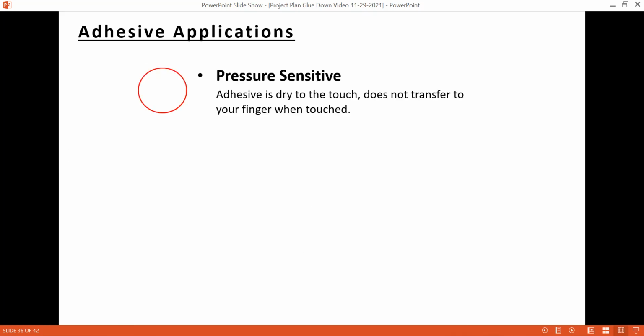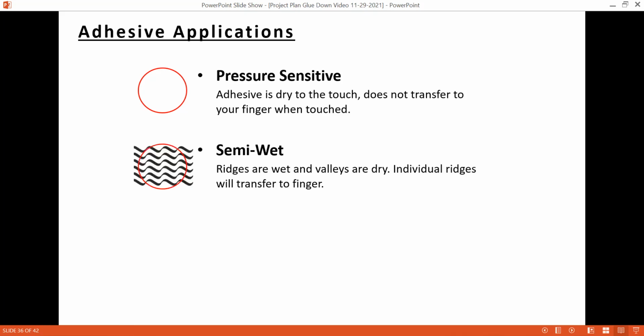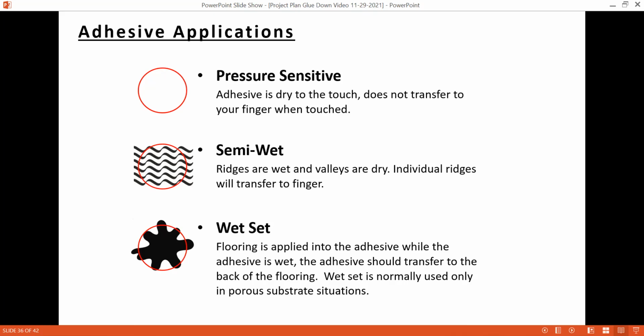Adhesive applications are often referred to as pressure sensitive. This is where the adhesive is dry to the touch. It does not transfer to the finger when touched. Semi-wet refers to the adhesive when the ridges are still somewhat wet and the valleys are dry. Adhesive will transfer individual ridges to the finger when touched and will transfer some of the adhesive to the back of the flooring. Wet set refers to installing the flooring while the adhesive is still wet. The adhesive will cover the finger when touched and transfer to the back of the flooring, achieving close to 100% coverage. Wet set is used only on porous substrates.